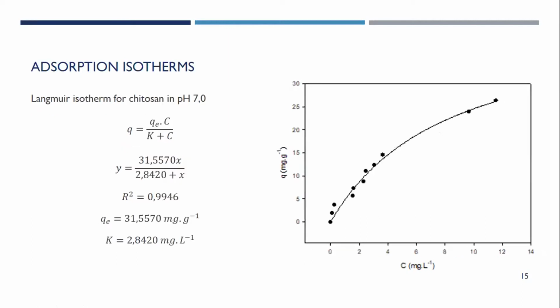The Langmuir adsorption isotherms were also built on nonlinear regressions, however following a different equation as shown. For Chitosan at a pH value of 7, the maximum adsorptive capability was shown to be 31.5570 milligrams per gram, and the balance constant, which also denotes the rate between desorption and adsorption rates, was shown to be